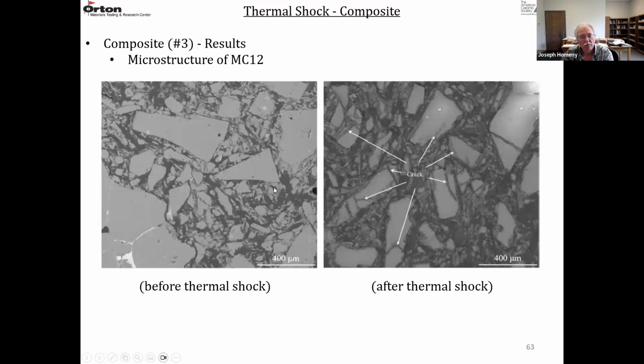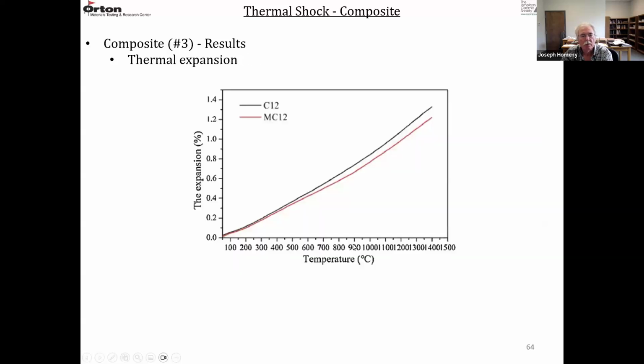And then the MC12, same thing here. Less fracture through the coarser particles. There's obviously less coarse particles, but it's more ductile. So there's more fracture at these interfaces and more fracture in the matrix than at these interfaces. Again, it's just difficult to see. And that fracture behavior showed up in the acoustic emission also.